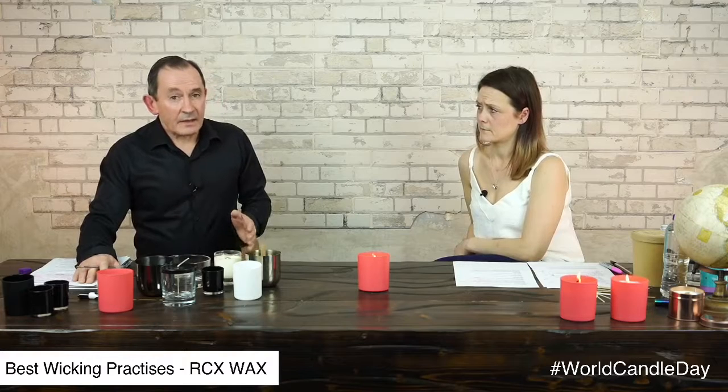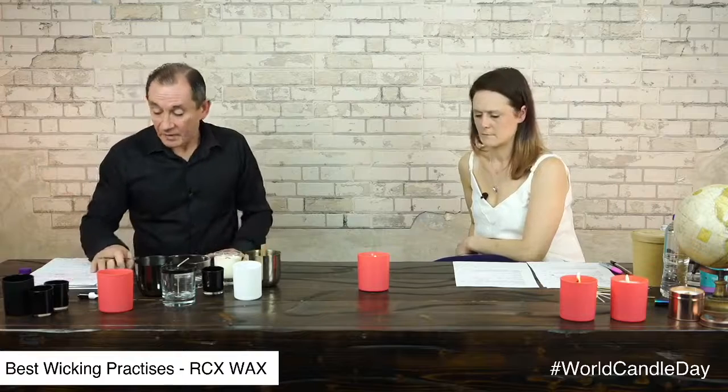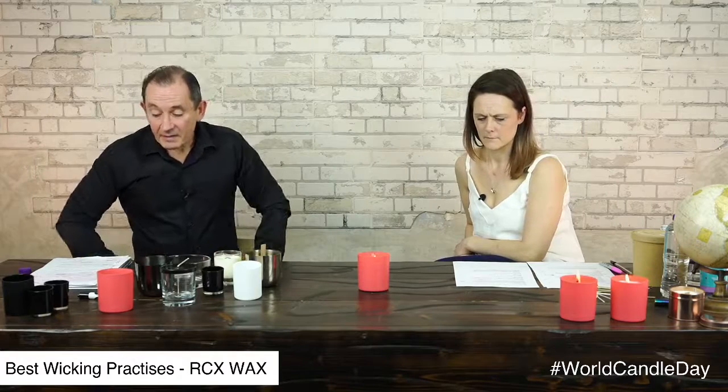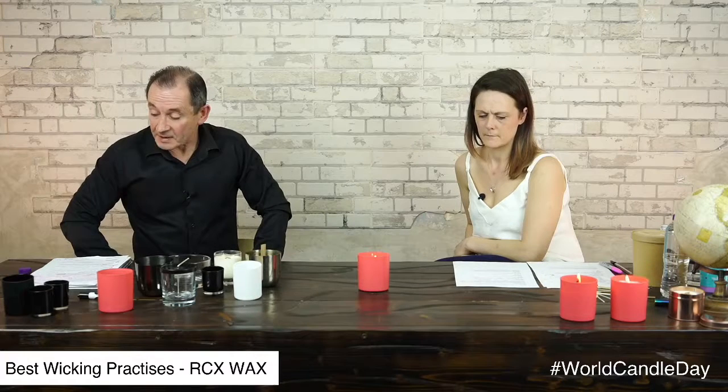You only really have to be conscious of that for perhaps the first 48 hours. After that, the candle is pretty much cured as much as it's going to cure. It's a crystallization process. After 48 hours crystallizing, it's not really going to change very much, and at that point you can be a bit more flexible in how you treat your candles. So, in summary, heat to 60, add your fragrance oil, pour it at 50 to 55, ideally in a heated glass if you can, and crucially, keep it at room temperature for 24 to 48 hours.